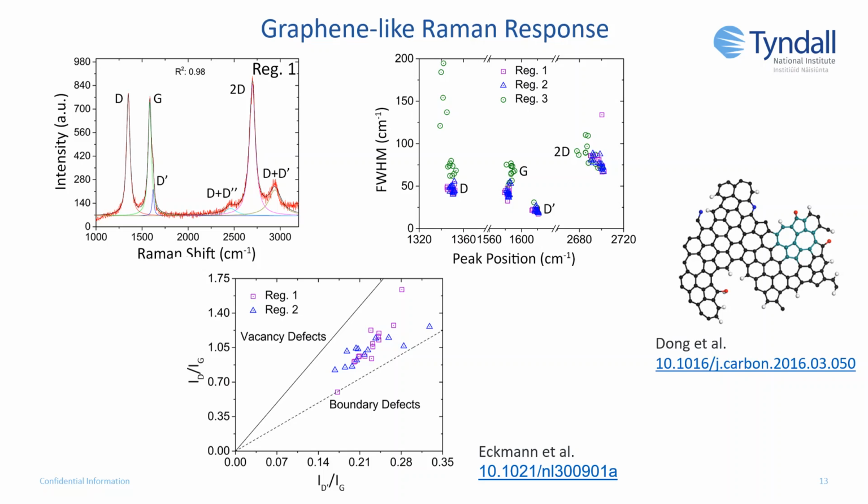At the beginning of this presentation, I noted that Dong et al. in their initial work demonstrated that their graphitic material was graphene-like. One of the most convincing arguments that we also demonstrate here is the Raman spectra from our sampled regions of interest. We see the presence of sharp G and 2D peaks characteristic of graphene-like material.